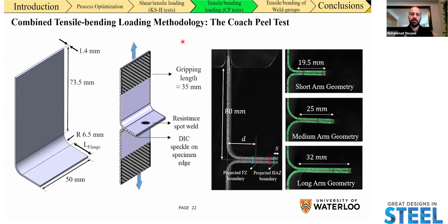In order to add data points in the tensile bending loading domain, we have to perform our Coach Peel mechanical tests in different geometries to change the ratio of tensile load and bending moment applied to the spot weld until the onset of failure. This is the methodology of the test.